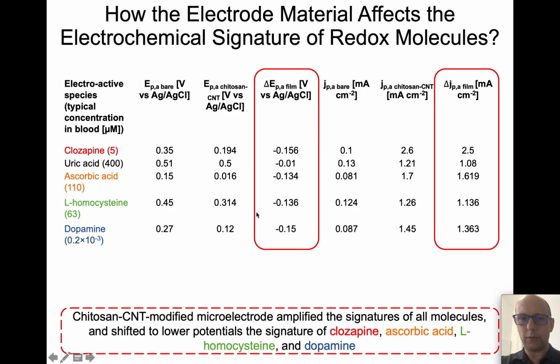So in this table, I would like to look at the 2 columns that are circled with a red line: how the peak shifted between the bare and chitosan-carbon nanotube, and how the current increased or decreased. What you can see is very interesting: other than uric acid, all the other redox molecules actually shifted the potential to a lower potential. So we can see that there is some kind of electrocatalytic effect of the carbon nanotubes on the molecules other than the uric acid. So by introducing chitosan-carbon nanotubes, we are already overcoming the challenge of masking electrochemical signals from the main interfering molecule that has a high concentration, which is uric acid.